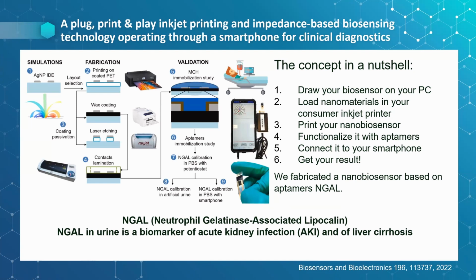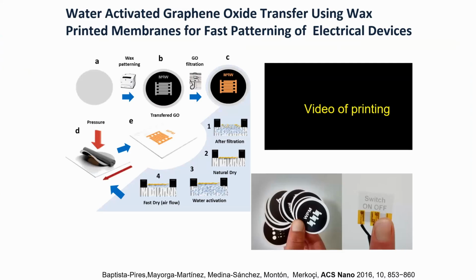impedance spectroscopy. Of course, the printing of the system is done everything using a consumer printer, and of course patterning this with a wax printer and laser etching to achieve the configuration, the structure of the electrodes we want. In this case, we're using silver nanoparticle-based inks.